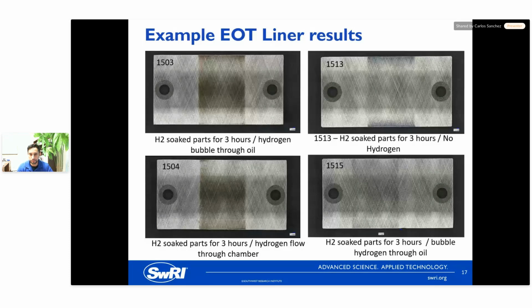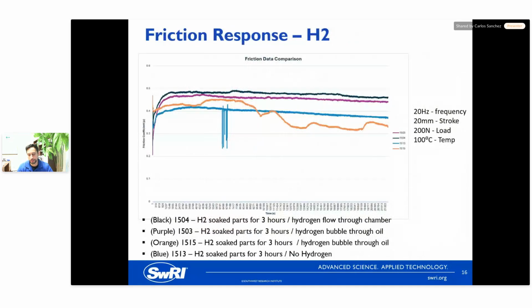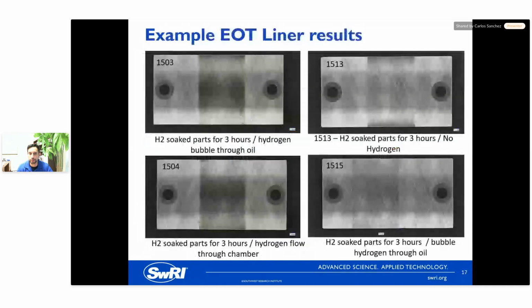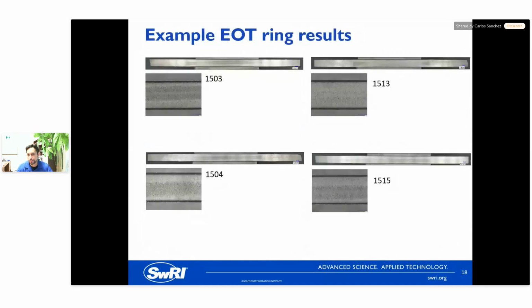And just go back. So I forgot to mention the test conditions that we ran. They're kind of in the corner there. So we ran at 20 hertz frequency, 20 millimeter stroke, 200 Newton load, and 100 degrees C in temperature. For those who are wondering what the test conditions were. Looking at the rings, you can see there's a little more wear on the rings on the left side.